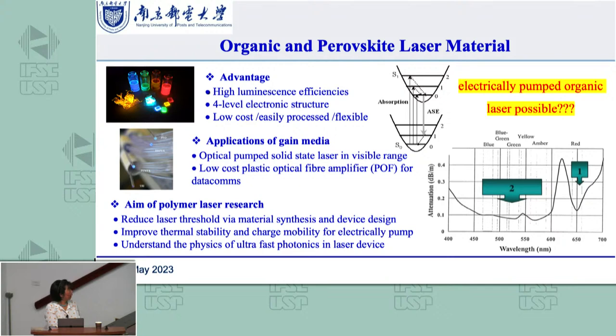To do that, in our organic laser work, we always consider how we can reduce the laser threshold so that the pumping energy does not have to be very high. Another thing is improving the thermal stability of the laser material. Because the laser needs a threshold, if we try electrical pumping, the current density could be very high, over several amps or 100 amps. In that case, the device can get very hot and can burn in a minute. So it's very important to improve the thermal stability. And also, the big disadvantage of organic materials is the low charge mobility for electrical pumping.